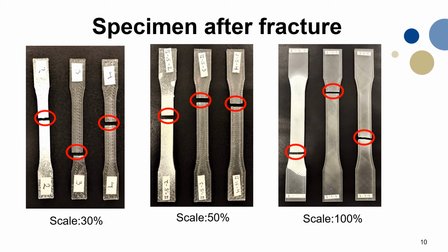And this is how the specimens look after fracture. As you can see, some of the specimens broke near the edge of the gauge length, and some of them broke in the middle. All of them have a shape of horizontal lines for the breaking, so none of them follow the raster angles of plus or minus 45 degrees.